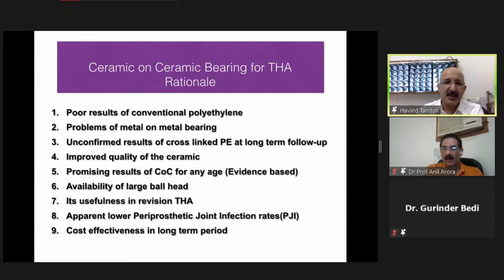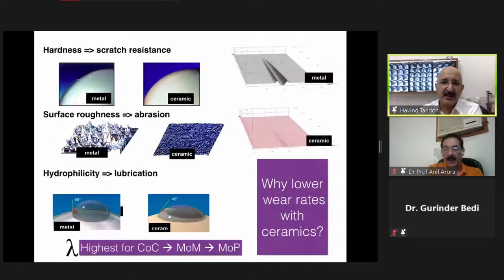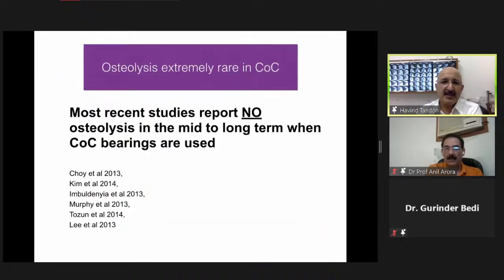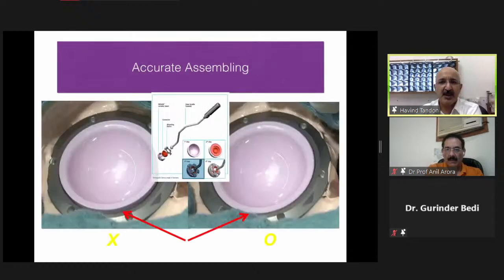the type of ceramic, the quality of ceramic had been improved, and all the complications related to breakage, squeaking had been taken care of. And now we could get very, very large heads by which we could reduce the wear further. And over the generations now, many studies have shown that in mid to long term, ceramic on ceramic bearings are having extremely low osteolysis or no osteolysis, giving rise to long-term benefit and survivorship of our THAs. But it has to be very exact while we are seating the insert of the ceramic liner.